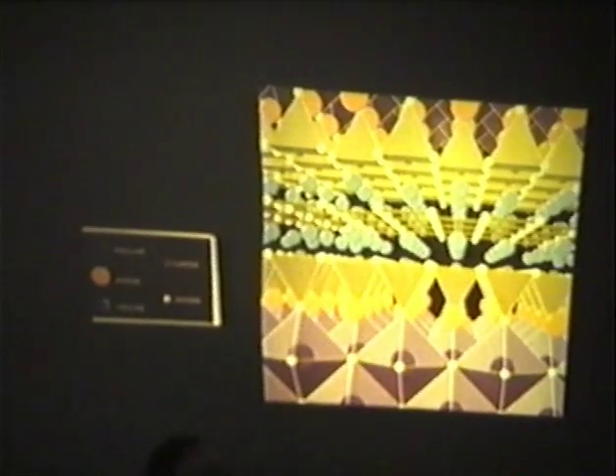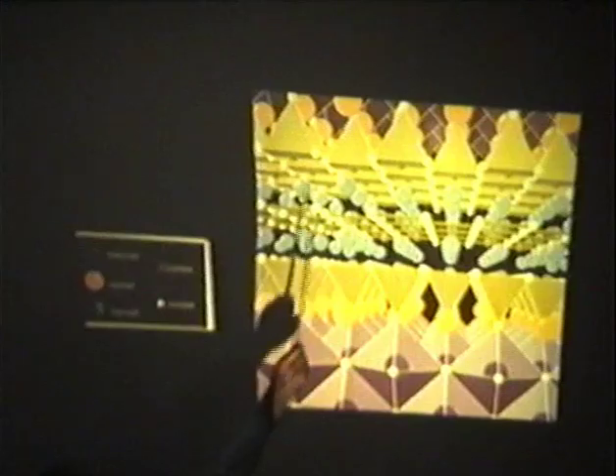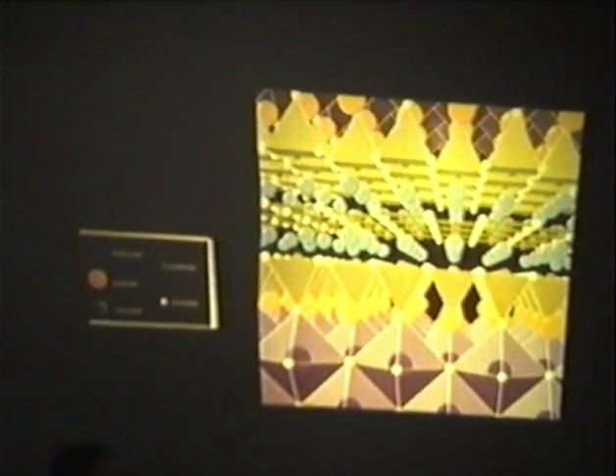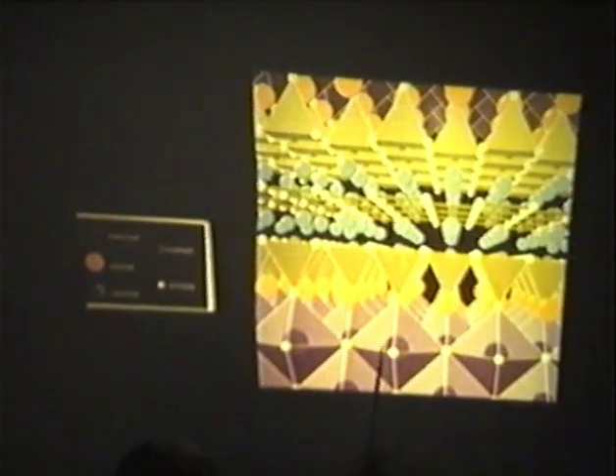And it's these copper oxide planes where part of the 2+ valence of the copper has been bled off by all this other stuff, all this decoration, barium, and in this case thallium, and a whole lot of other things. It's bleeding off a little bit of the valence, so the copper valence is a little bit greater than 2, which is responsible for the mechanism of the superconductivity. This is the engine room of a superconductor, the new superconductors that were discovered in 1986. And in fact, the supercurrents, the Cooper pairs, only propagate along these planes. You do not get superconductivity at right angles to these planes. And that was new.